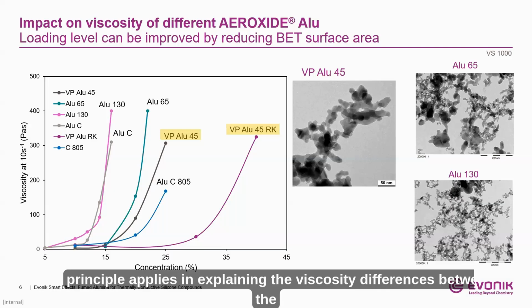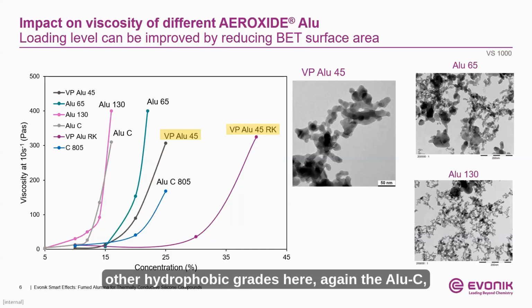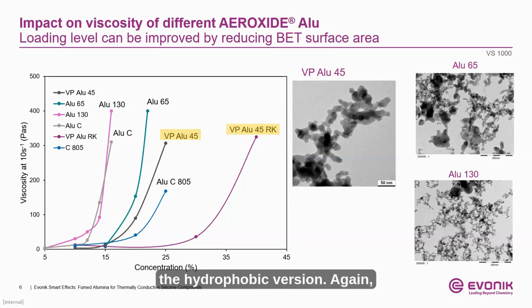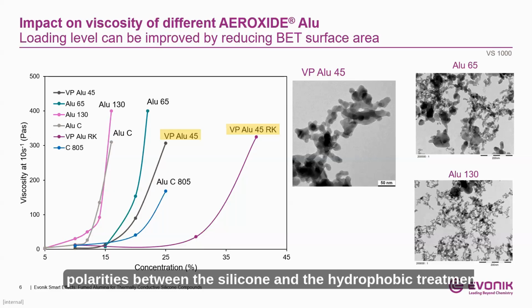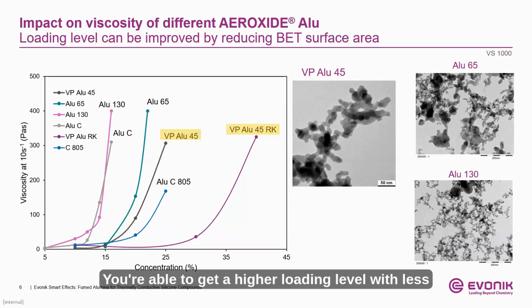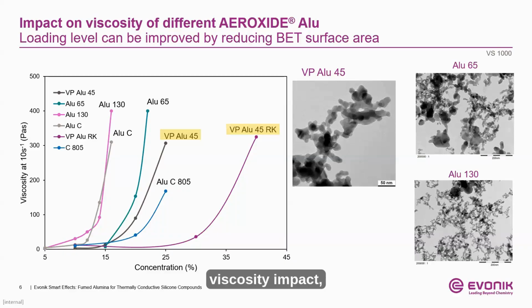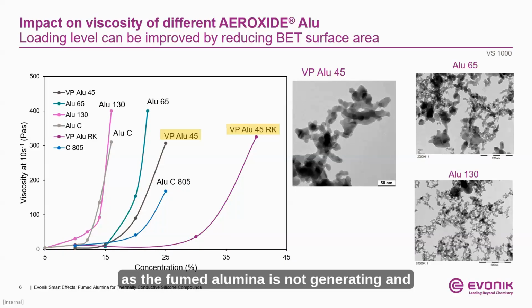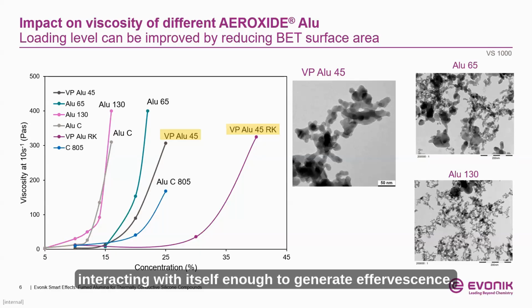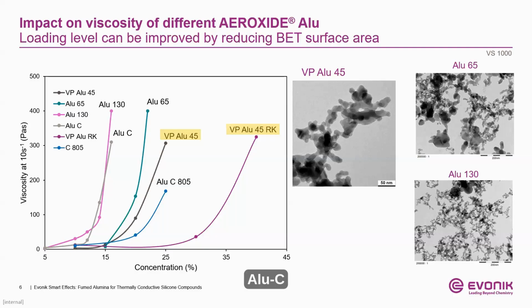The same principle applies in explaining the viscosity differences between the other hydrophobic grades here. Again, the AluC, the hydrophilic version, and the AluC 805, the hydrophobic version. Again, the same principles would apply due to the similar polarities between the silicone and the hydrophobic treatment. You're able to get a higher loading level with less viscosity impact, as the fumed alumina is not interacting with itself enough to generate efficient viscosities in these systems.